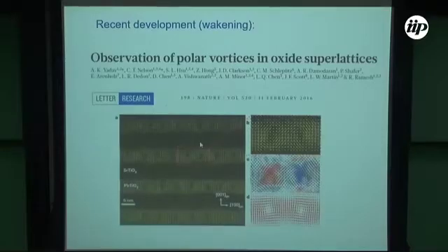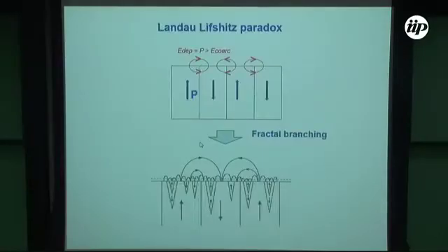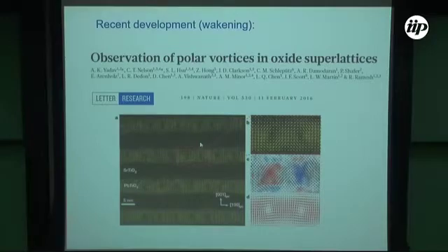So this was the state, and it was more or less a quite sleepy atmosphere till 2016, when Nature journal started to pay attention to this effect, namely a group from Berkeley. Because experimental technique is now developed very highly, they are really able to observe the displacement of individual atoms. They claim observation of polar vortices in oxide superlattices. In principle, they observe exactly this structure, and they claim that we have some kind of vortex structure in ferroelectrics.